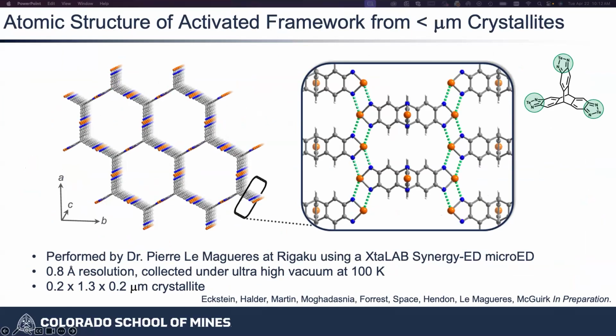Yeah, so it's annoying nomenclature. The tellurium is the donor, the nitrogen is the acceptor. Oh, sure. Yeah. It's like hydrogen bonding. It's really weird. Right. So with our chalcogen bonding work, we've been still pretty stuck on these chalcogen and diazo groups because they behave super well. We have a whole other platform on halogen bonding. And in that case, we've done a lot of different work looking at different heterocycles, different spacing, different compositions, all these things. And for that, we do a lot of just very simple DFT using ESP maps as a kind of first principles prediction of electrostatic interaction.